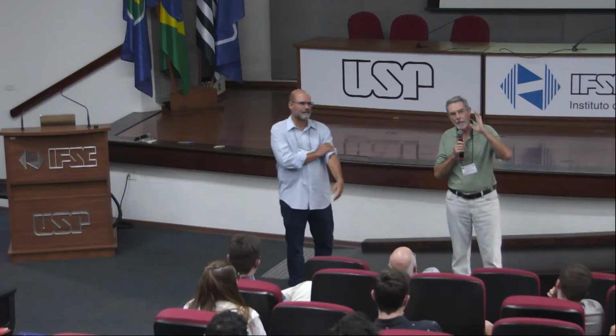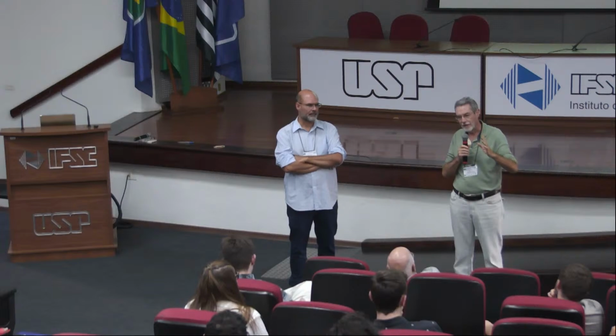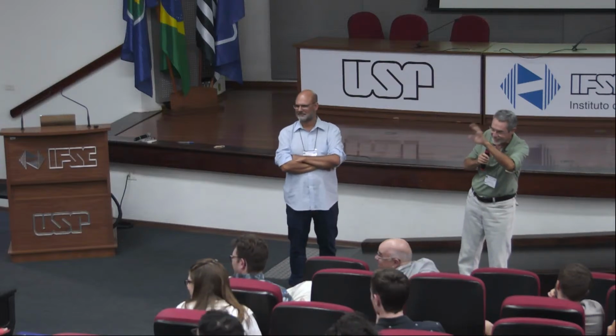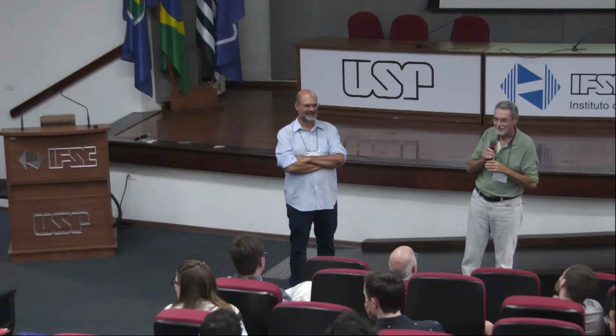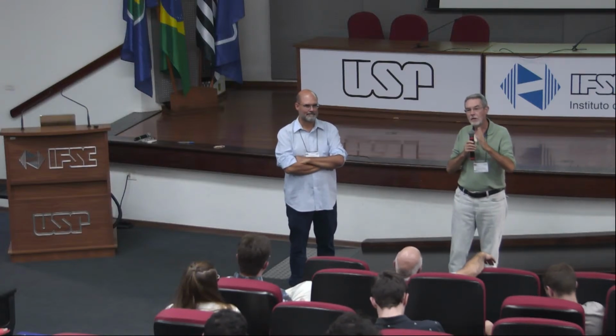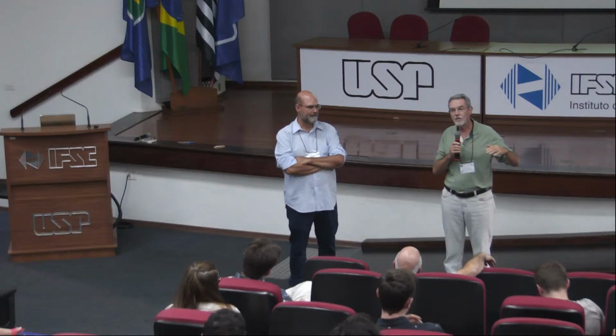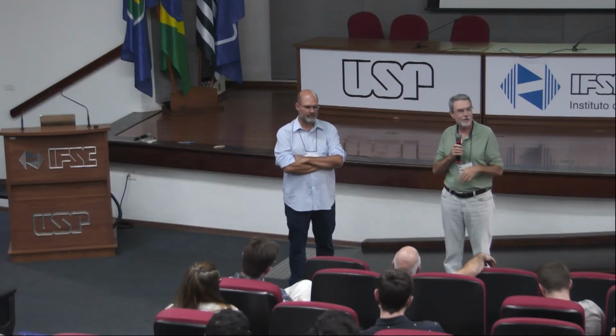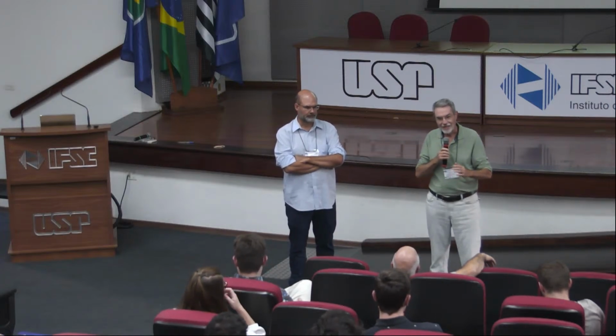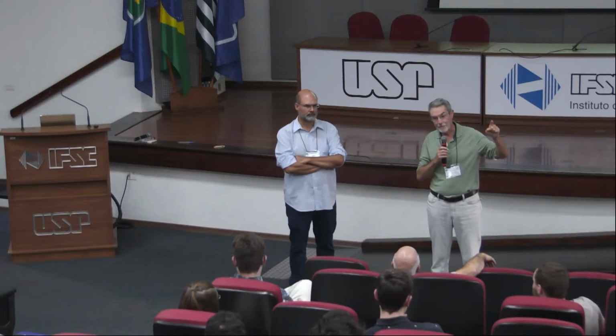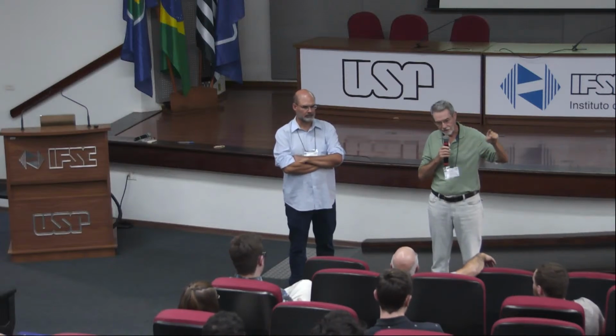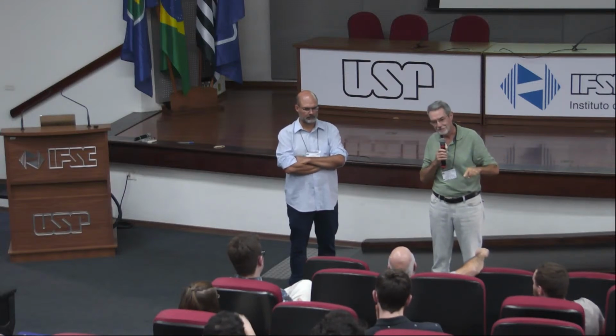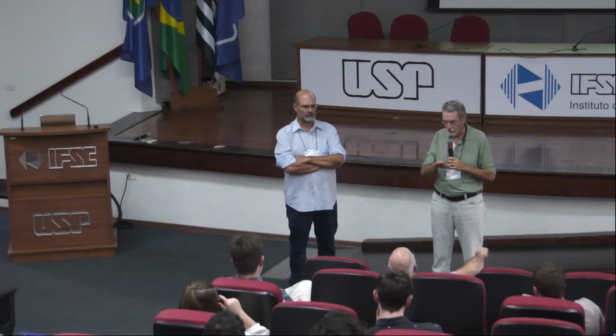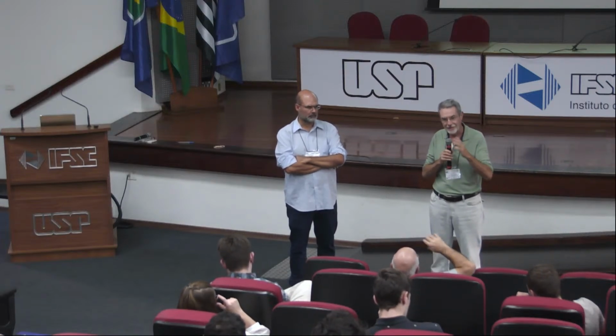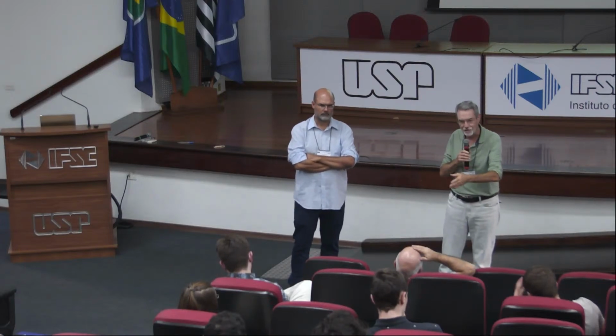So let me tell you something that I did not show in my talk. All those maximum temperatures of nucleation are incorrect. All of them, right? Elena, there is Elena. She discovered that. The thing is, below Tg, you have these extremely long induction times. So if you wait for 500 hours or so, you reach steady state. In the steady state, the nucleation rate below Tg is higher than above Tg. All the maxima for homogeneous nucleation are below the laboratory Tg. I'm talking about the DSC Tg, you know.